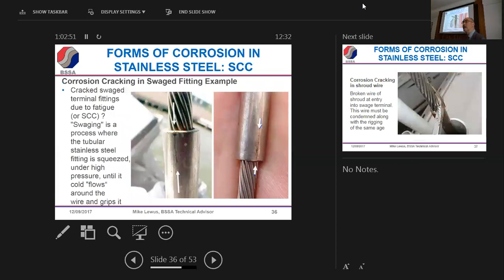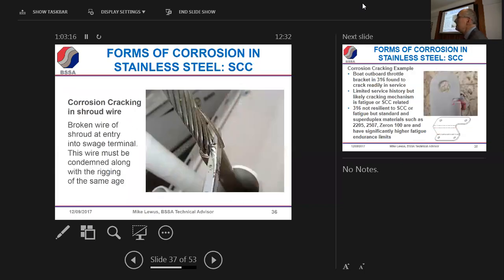Now, unless you do a lot of detailed metallography, you can't be certain, but it's very likely that sometimes these are over tightened when they swage. There's a high stress in those at the ends of these fittings, and it's a bit out of sight that there could be some crevicing on the other side, some pitting, which has allowed stress to be relieved. It's ultimately opened up a crack. So you see that kind of thing. You see broken wire on rigging and shrouds.